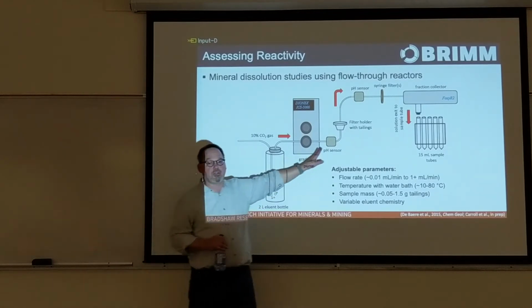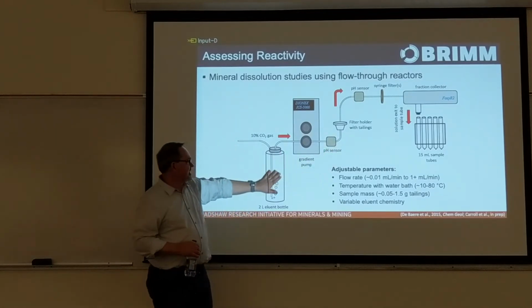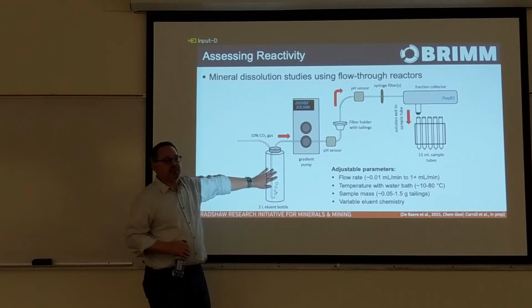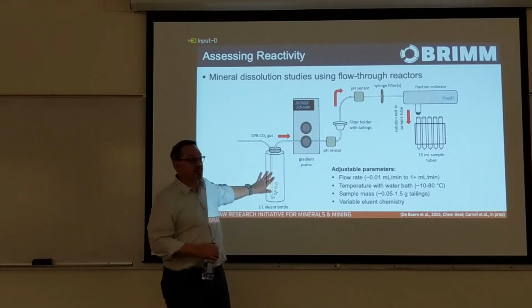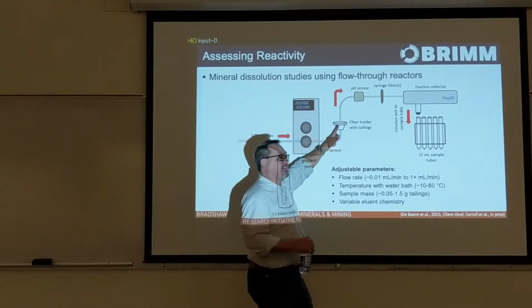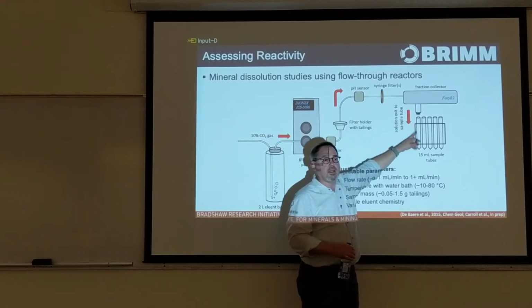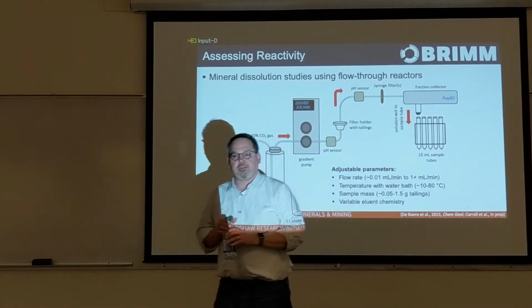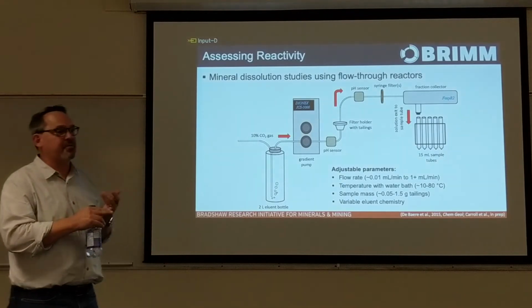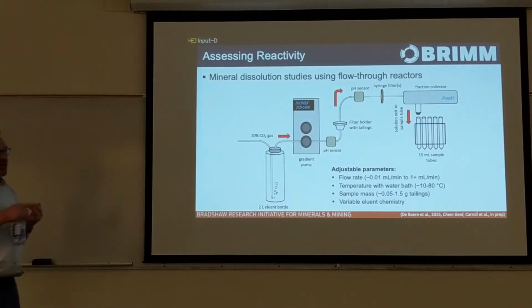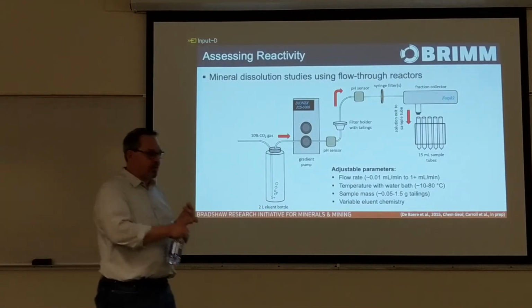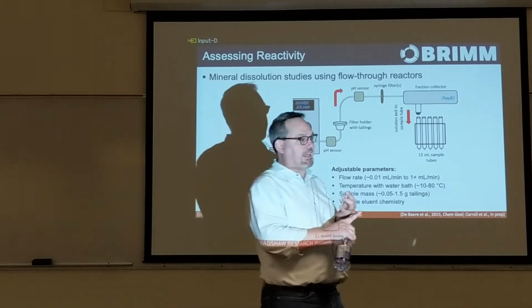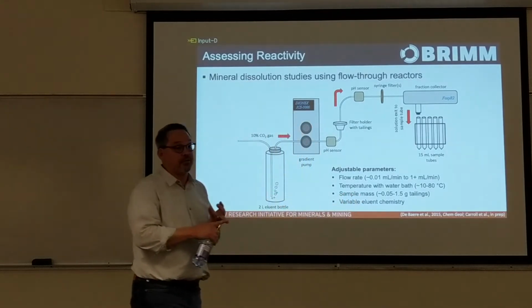We're doing this at room temperature and pressure. We use distilled water that has 10% CO2 sparged through it. So we're using no special chemicals, and we're using flue gas CO2 concentrations as a source of acidity. That acidity then drives mineral dissolution, and we generally stop counting after 2 days. So essentially, we're measuring how much magnesium we can get off of tailings at room temperature and pressure with no special chemistry, using only flue gas for acidity, and stopping after 2 days.